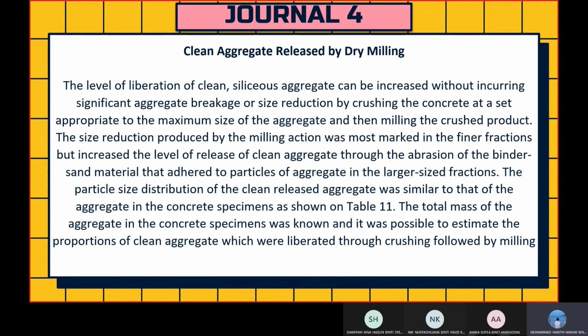So for the clean aggregate released by dry milling, the level of liberation of clean siliceous aggregate can be increased without incurring significant aggregate breakage or size reduction by crushing the concrete at a set appropriate to the maximum size of the aggregate, and then milling the crushed product. The size reduction produced by the milling action was most marked in the finer fractions, but increased the level of release of clean aggregate through the abrasion of the binder sand material that adhered to particles of aggregate in the larger size fraction. The particle size distribution of the clean released aggregate was similar to that of the aggregate in the concrete specimen, as shown in table 11.